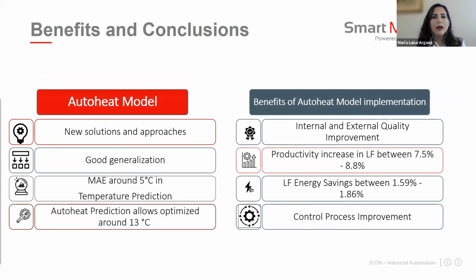So now let's conclude this webinar. Here it is essential that nowadays we provide new solutions and approaches to share knowledge in the company. The auto-heat model demonstrates good generalization. Therefore, it is suitable for making predictions in the future without supervision. And the mean absolute error was around 5 Celsius degrees in all temperatures. The auto-heat model prediction allows optimized temperature around 13 Celsius degrees. And with respect to the benefits, we can achieve an internal and external quality improvement, productivity increase in the ladle furnace between 7.5 and 8.8%, LF energy savings between 1.5 and 1.8%, and a better process control.